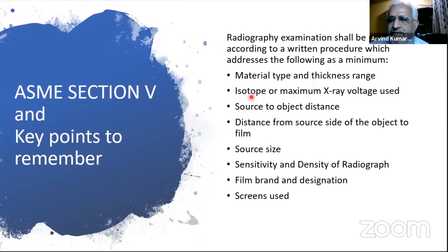Then whether you are using X-ray or gamma radiography, the source to object distance, distance from source to the film, size of the source, sensitivity and density of the radiograph that is required, the film brand and designation, that means whether NDT 65 ultrafine film or which type of film is used, and the screens which are used to protect against backscatter and other things. And another thing not mentioned here, but it is assumed to be required, is the acceptance standard. We know what the acceptance standard is. Then only you can do a proper interpretation.